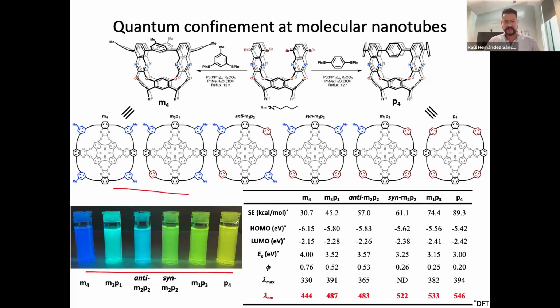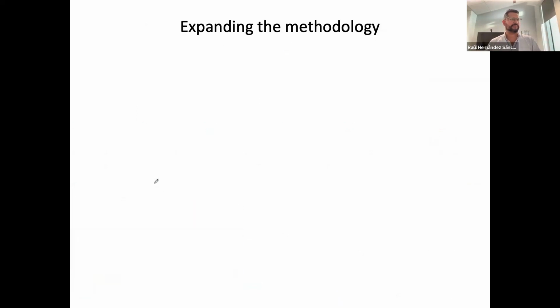And so the way we understand this, and I'm not going to go into all of the DFT studies that we've done, is that as you go from right to left, you're limiting the size of the conjugation pathway, and therefore changing the box. So you can think of the particle in the box example. And so you're shrinking the box more and more, and therefore you have this blue shifting of the emission as you go from the fully conjugated species to this meta, where now you have a large dihedral angle or torsion angle right there.